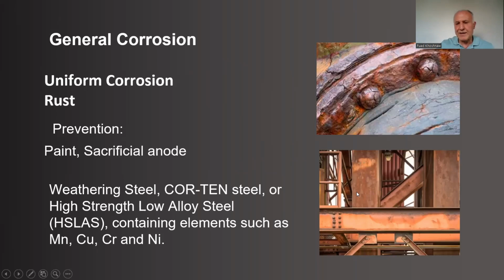And the advantage of that is, with time, this oxide layer protects more and more, preventing corrosion from happening. So we need to make a big difference between rust and some other types of steel alloys which already have resistance to corrosion, but whose appearance is somehow similar. It is a natural brown oxide layer, but there are no cracks or flakes as has been seen here. So it just looks a bit smooth. It is a rough surface, but compared with this one, there are no flakes, so you can make this difference.